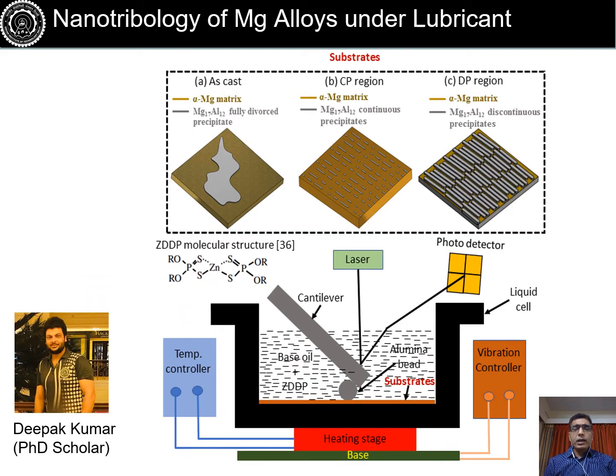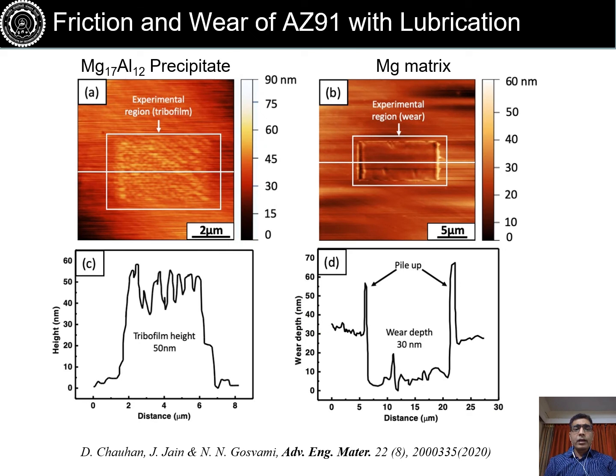Apart from aluminum alloys, we are also interested in magnesium alloys. So my student Deepak, who has done some work on how these reactions happen on magnesium surfaces, magnesium alloy, which is AZ91 aluminum zinc alloy. So in this alloy, we have either cast alloy, which has large precipitates, or we can age harden these alloys, and that is done to improve their mechanical properties, but age hardening results in finer precipitates. So how the microstructure affects the film growth was investigated in this work, and we found that ZDDP forms very nice tribofilm on large precipitates. So this is a flat surface of a large precipitate, Mg17Al12 precipitate, and around 40-50 nanometer thick film has been observed.